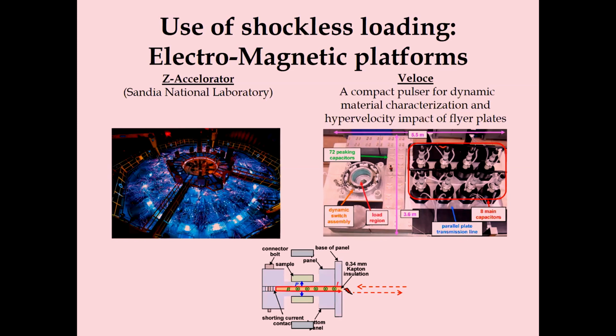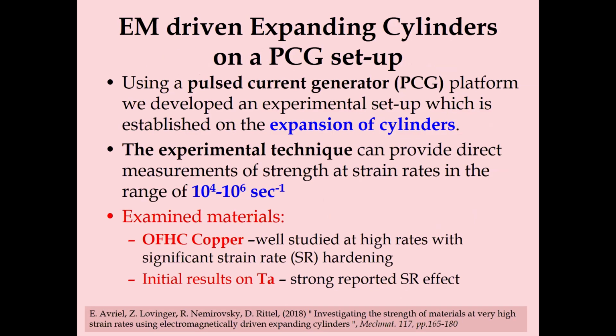So instead of impacting it or shocking it, we're just using very fast magnetic forces, but this ramp loading is not getting the heating which we're getting through shock. So having this in mind, when we were looking to examine the behavior of strength of materials, we were looking also to use a setup on the pulse current generator, and we're using the technique that we developed. We're using a pulse current generator using expanding cylinders. Using this technique, we could reach very high strain rates between 10 to the 4 to 10 to the 6. I'm going to explain this in the next couple of slides.